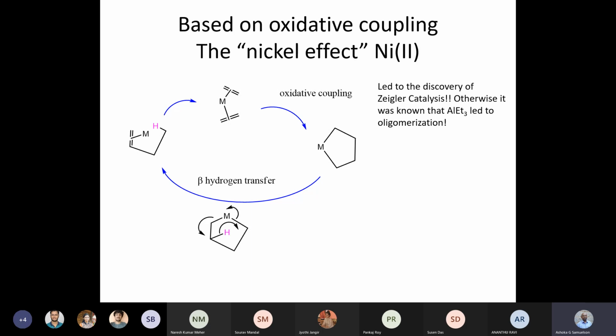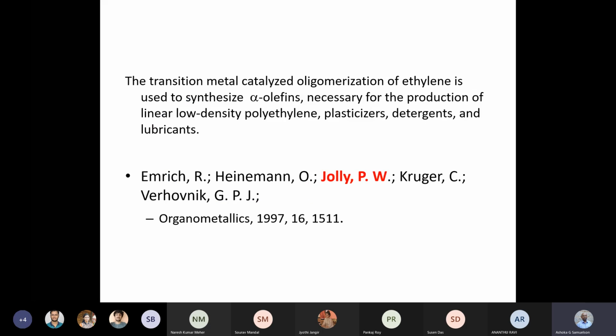So this beta hydrogen transfer can stop the reaction, and if it doesn't stop the reaction, you can actually have polymerization. So they ended up looking at other metals, and soon they found out that if you used group 4 transition metals, you can make polymers. And the whole area of Ziegler developed this whole area of polymerization.